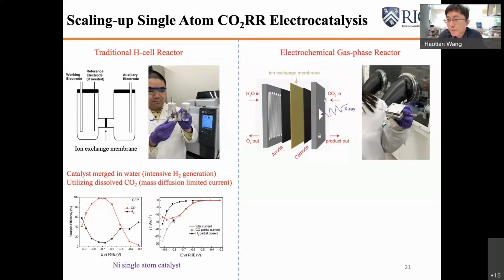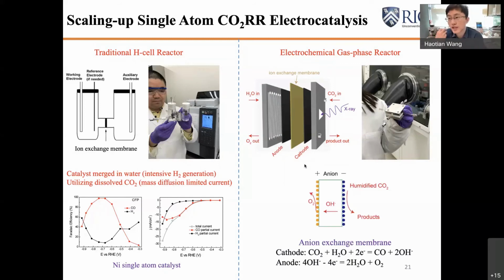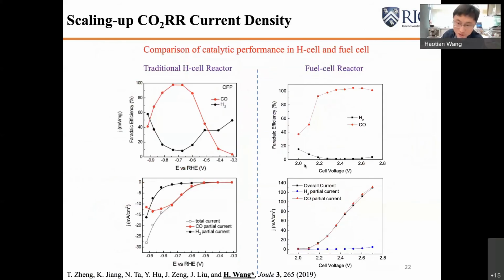But based on our experience in the previous fuel cell studies, now we want to flip over the concentrations of CO2 and water. So in this case, we're using a membrane electrode assembly. And now we can purge in high-purity CO2 gas. And of course, it needs to be humidified because we need to have the water molecules to provide the protons. But in that case, we can provide more than 95% of the concentration coming from CO2. And this is a gas-phase reaction, so that you won't be limited by the mass transport of CO2. And this is an important part of the cell engineering.